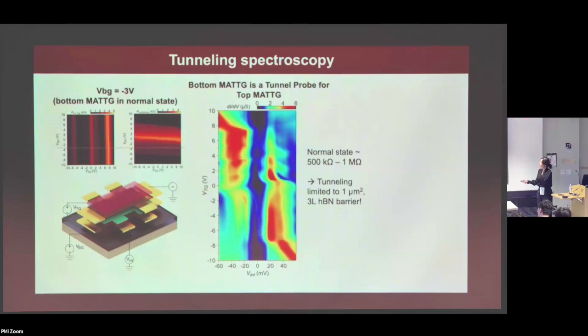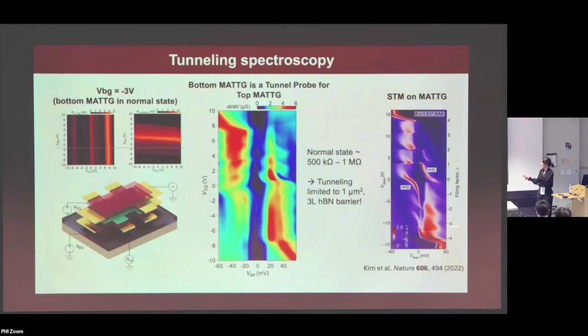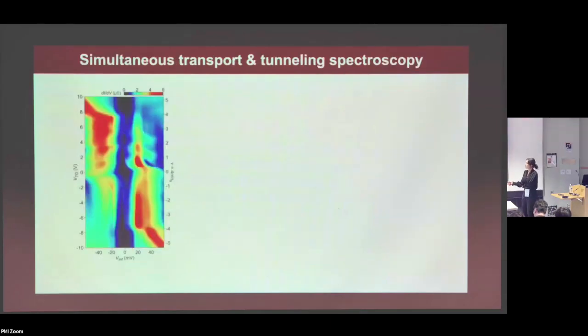You can also compare with STM on MATTG, and the large scale features, you can see, are very similar. So you can take a look at what this map tells you. What's most evident are these high density of states features where it goes away. And these are exactly the same features that we saw for the fourfold symmetry breaking. That's called the cascade of transitions, and that's already been seen in many previous measurements, including STM. So that's not new. You have this symmetry breaking, and that should be happening.